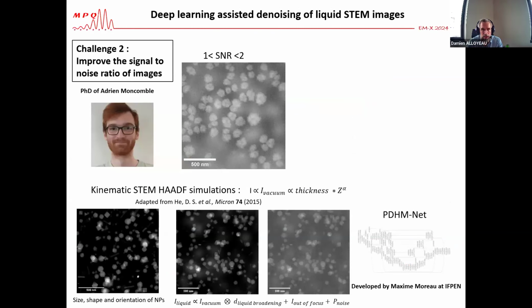Now, the second challenge I wanted to discuss is the necessity to work at much lower dose rates, because we want to minimize the electron beam effect. And if you want to meet this challenge, you need to improve the signal-to-noise ratio of images. Actually, when you work on those videos, even with gold nanoparticles, video processing is a nightmare, because even with gold, the signal-to-noise ratio of those nanoparticles is very poor, between 1 and 2, because you cross this thick layer of liquid. Additionally, your background is not at all homogeneous, because a lot of particles grow on the opposite membrane, are out of focus, and drastically contribute to the inhomogeneous background of your images.